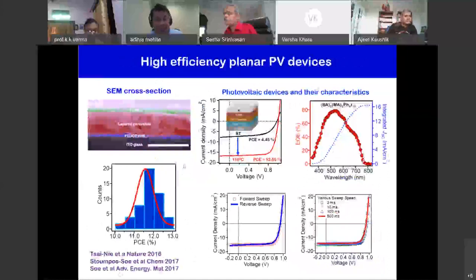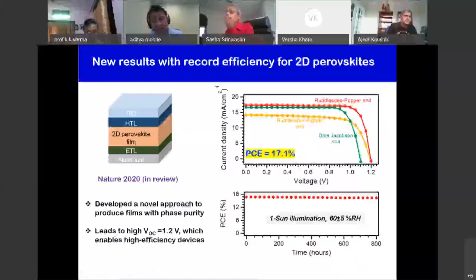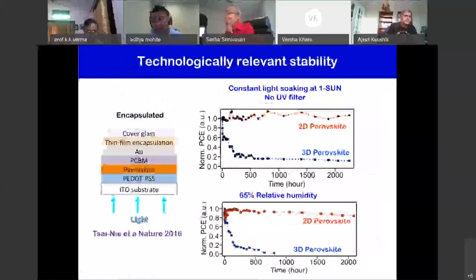which had about 12% efficiency at that time. We've of course improved this to about 17%. But the most important thing, and I'll close with this slide, is that in comparison to our 3D perovskites, the 2D perovskites were extremely stable.